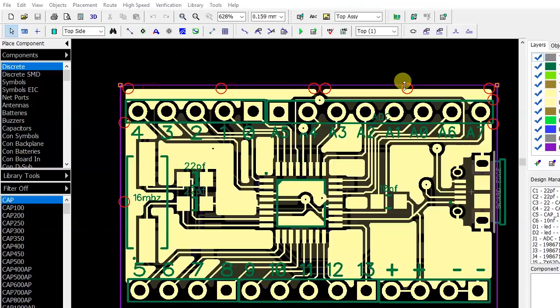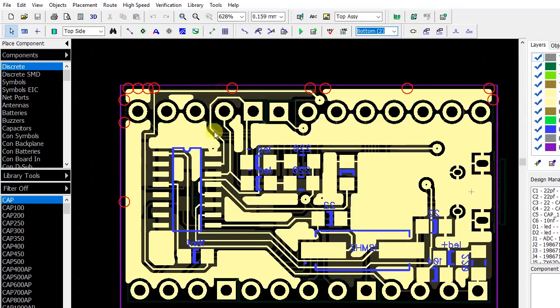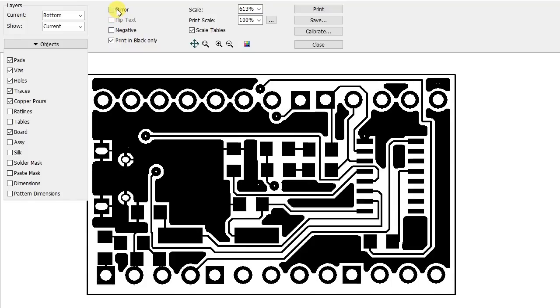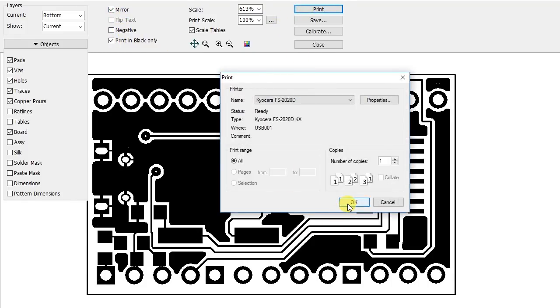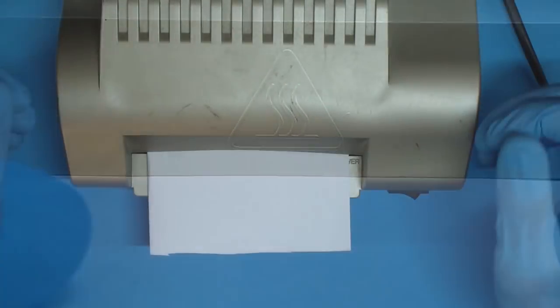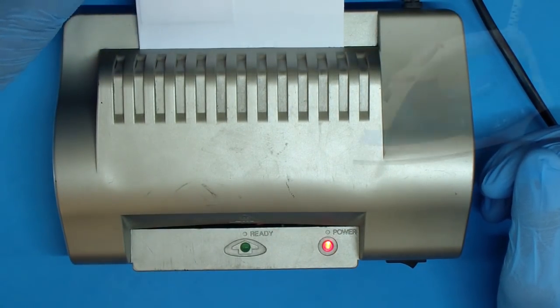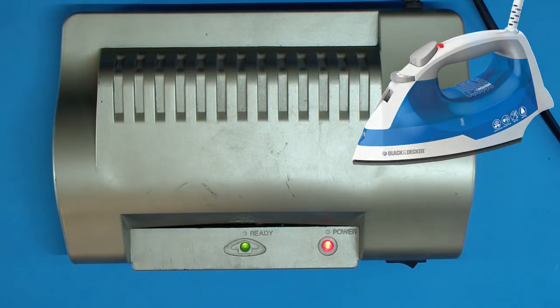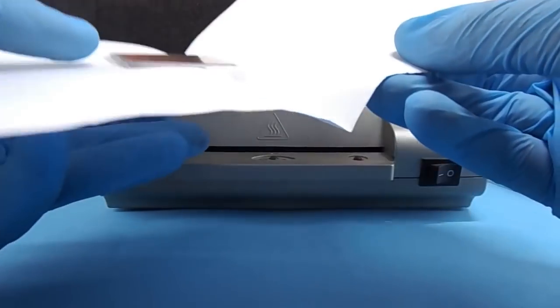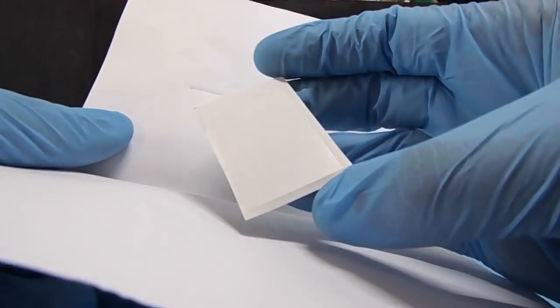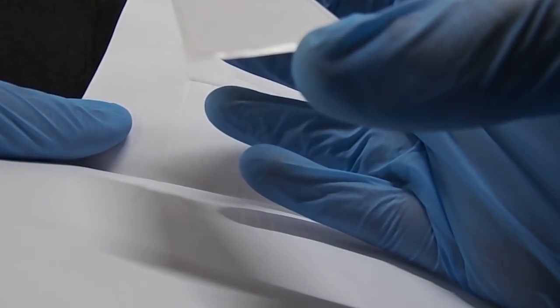In this video I'm going to make double-sided PCB. I will apply toner transfer to the bottom side and photosensitive to the top side. Let's see which method will succeed giving us good traces. I am printing my design mirrored on glossy paper, then transfer it to the PCB using heat and pressure. In my case I am using a PCB laminator. You can use clothes iron but sometimes it fails to get even temperature on the whole PCB. It's very important to clean the blank PCB with a steel wool and liquid soap before transferring the toner and never touch the copper anymore by your hands.